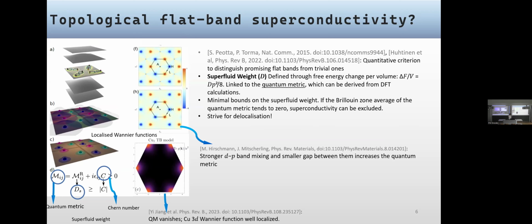The idea is that this superfluid weight, which is like free energy per volume, if non-zero, basically guarantees the existence of a superconducting pattern. It was linked to the topological properties of the orbitals through the Chern number, meaning that if the orbitals that create the flat bands are topologically non-trivial, then it's already a necessary condition for the superconductivity to exist there. Meaning that if they are topologically trivial, then we can pretty much guarantee it's not there anymore. And further, the theory was improved for multi-band systems and for time-reversal symmetry broken systems and so on.